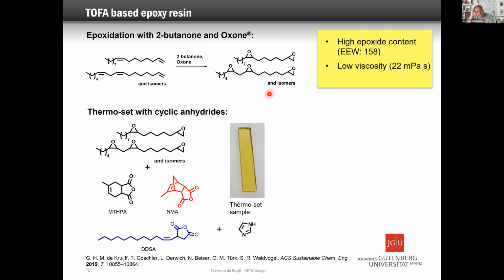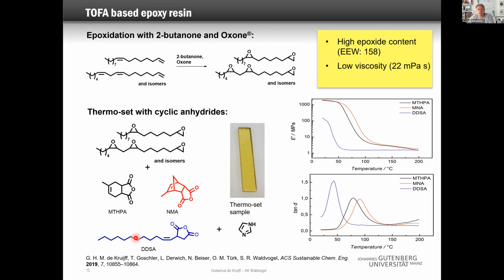And if you compare that, if you make a thermoset of that with cyclic anhydrides, these are common ones which are used. We just don't use the fossil-based versions, but something which is biogenic derived, and the thermoset you get here is remarkable. The qualities are quite nice. Depending on the anhydride, you get different qualities in when the thermoset starts. The low viscosity is of interest because then you can make very fine structures out of it. And therefore, I think there's a way to use the tall oil in this way.